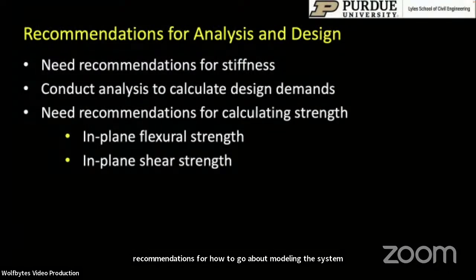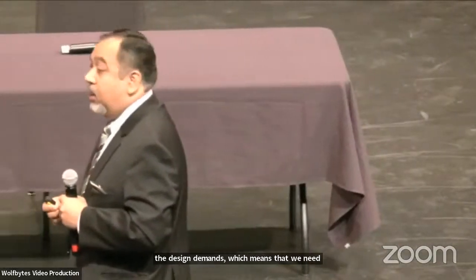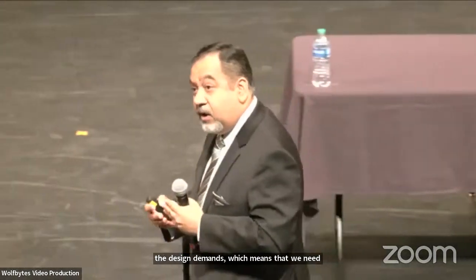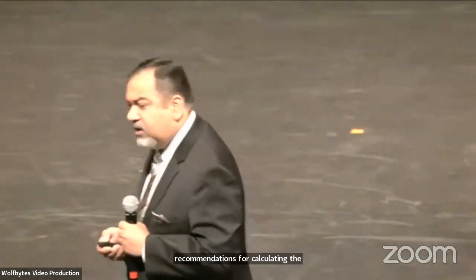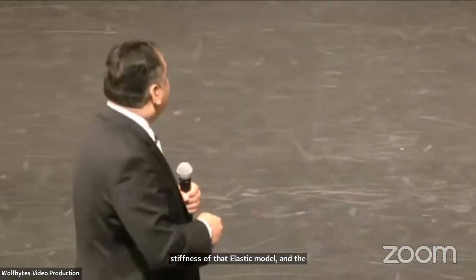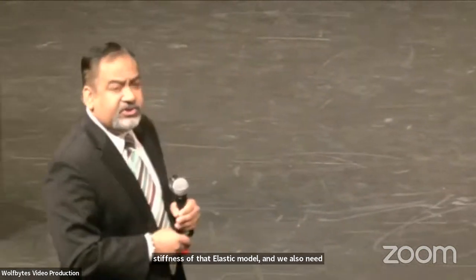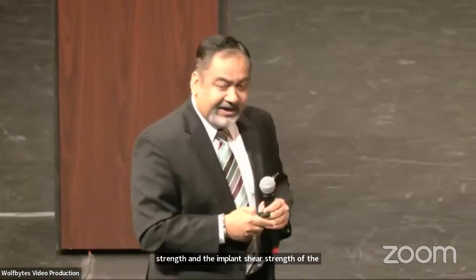So we need recommendations for the stiffness of this composite system, because we want to conduct analysis in particular to calculate the design demands, which means that we need recommendations for calculating the stiffness of that elastic model. And we also need recommendations for estimating the in-plane flexural strength and the in-plane shear strength of the system after the demands have been calculated.